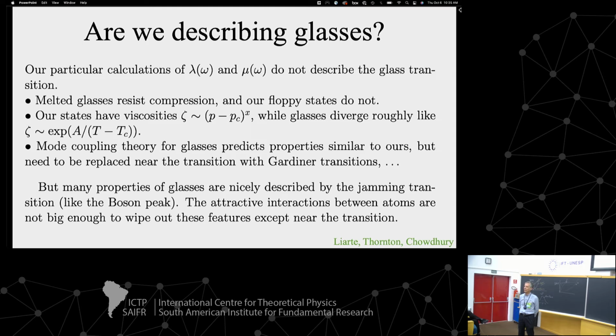But what you can do is, if you take a glass and it's very big, these elastic moduli concentrate. So if you take two different pieces of glass, more or less you get the same value. But then you can look at the fluctuations. You take two different glasses, and you look at the difference between their shear moduli. And this difference is small. It scales like 1 over root of the volume of the system. So in the infinite system size, they are essentially the same.